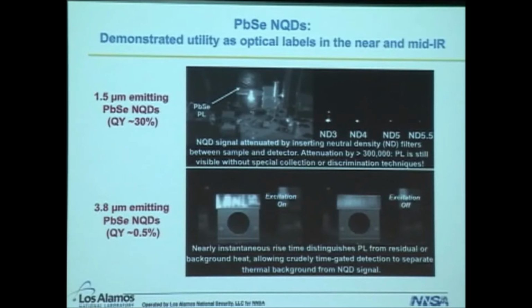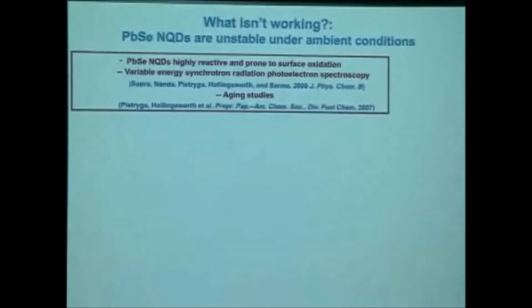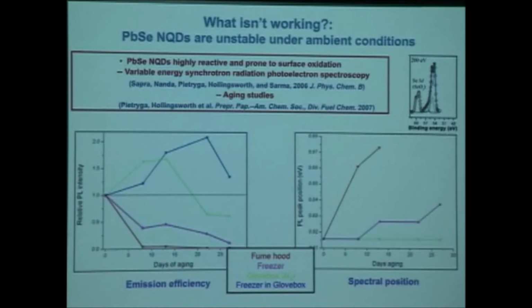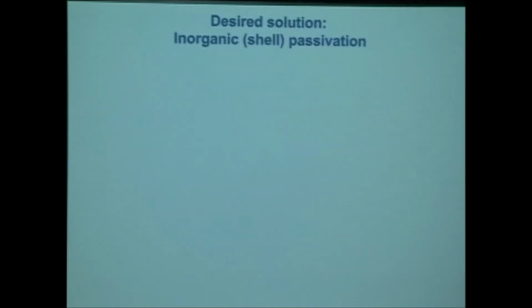We were interested, for various reasons, in using these as optical labels in the near IR and the mid IR. And indeed, you can clearly distinguish the emission from the quantum dots from background heat by doing simple time gating techniques. What wasn't working with lead selenide was stability. They tended to readily oxidize. We demonstrated, using variable energy synchrotron radiation photoelectron spectroscopy, that the selenium on the surface was clearly oxidized over time, diminishing our photoluminescence and also causing significant blue shifting over time.